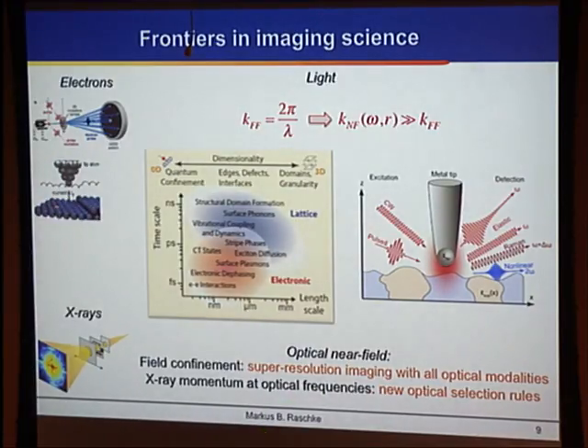That also means that when you normally plot optical transitions vertically in momentum space in a dispersion diagram, we can now access new optical selection rules, because we are no longer confined to these vertical transitions in the momentum diagram. So these are the key features again: deep sub-wavelength spatial resolution down to a few nanometers with new optical selection rules. And this is essentially what the talk is about.